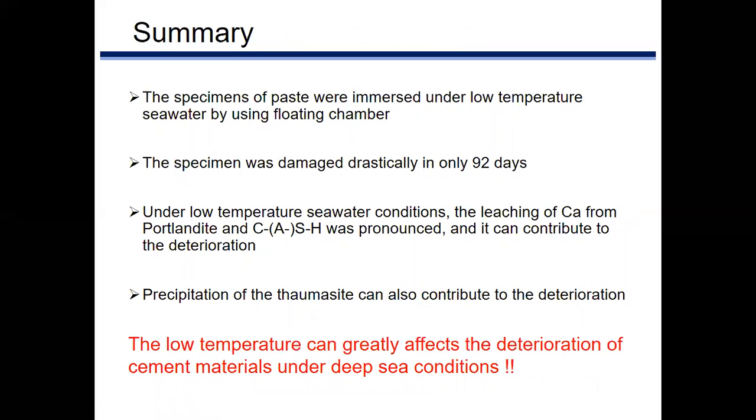Finally, I'd like to summarize the main findings of this study. The specimens of paste were immersed under low-temperature seawater by using floating chamber. The specimen was damaged drastically in only 92 days. Under low-temperature seawater conditions, the leaching of calcium from portlandite and C-S-H was pronounced, and it can contribute to the deterioration.